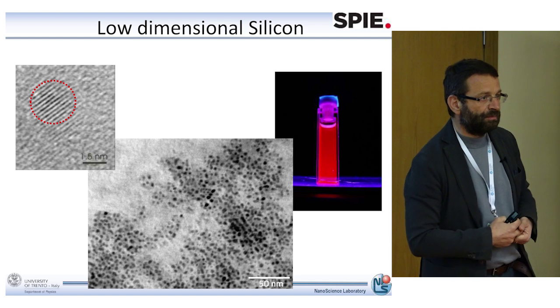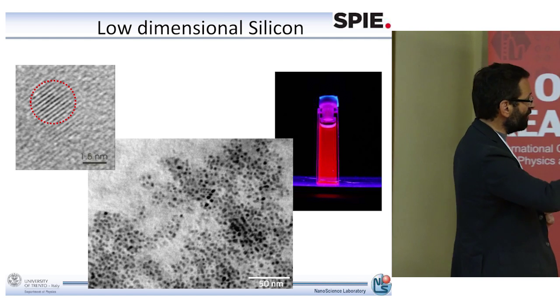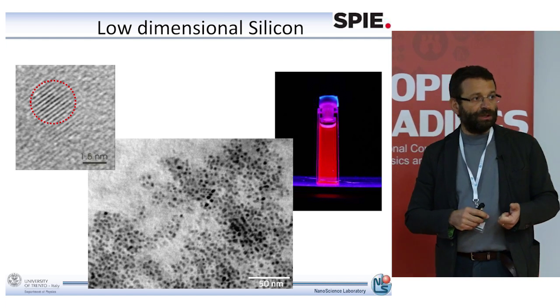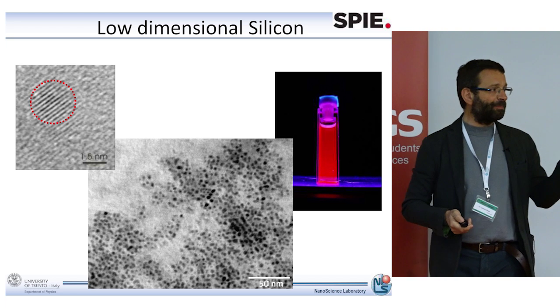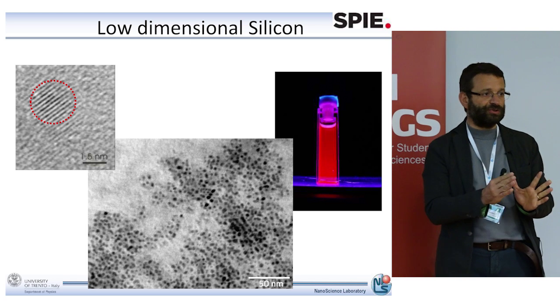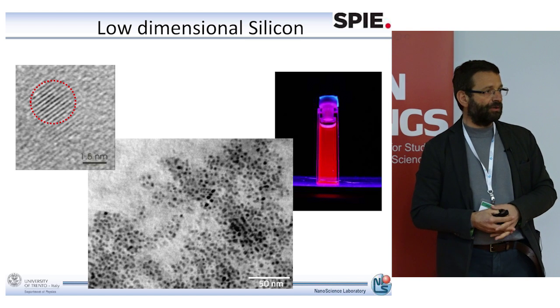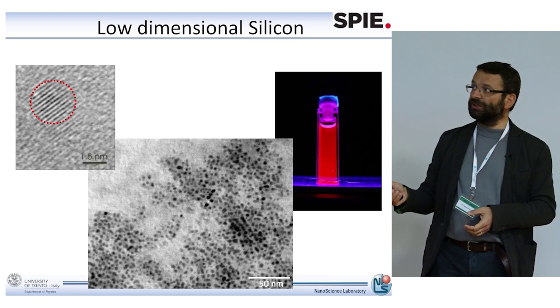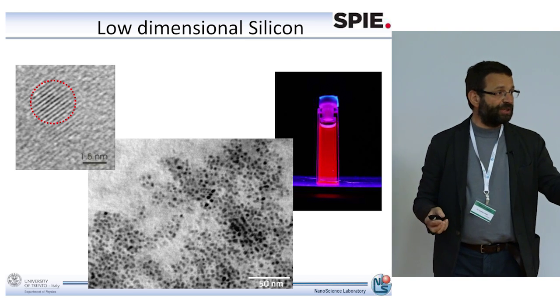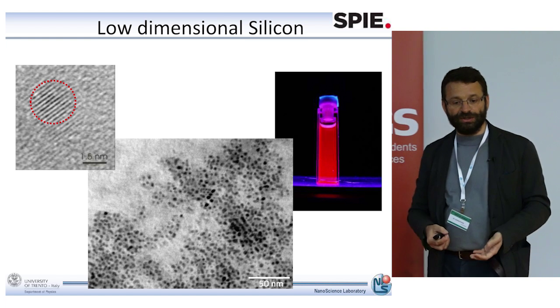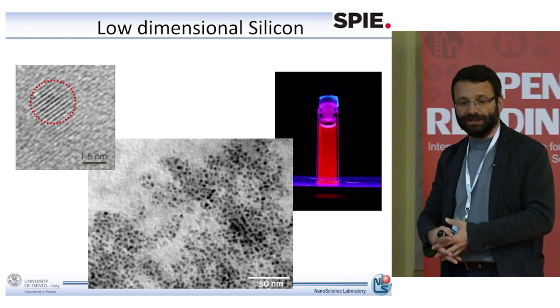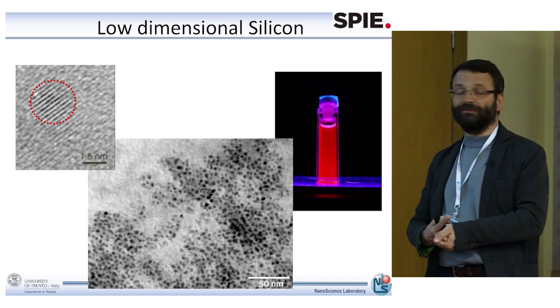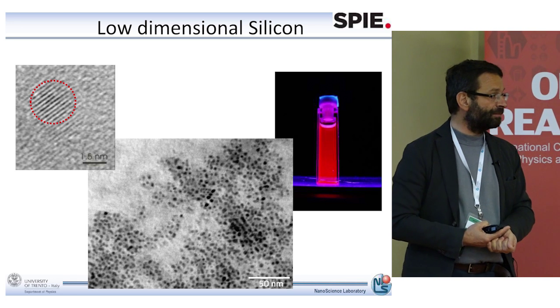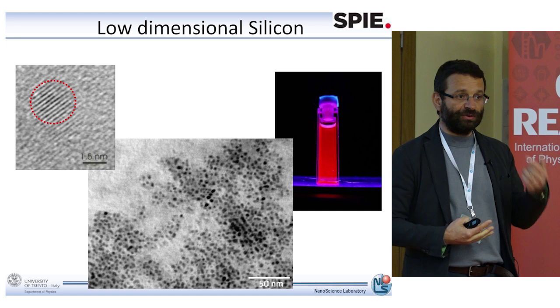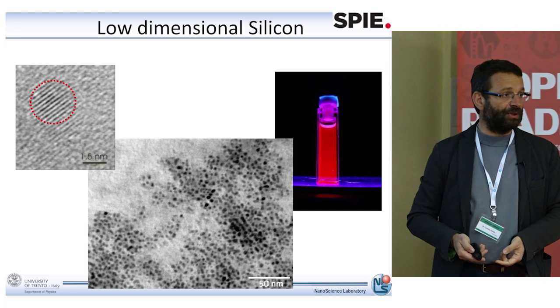Efficient, strong light emission. And the second fact is that the band gap of silicon is changed by reducing the dimension of the silicon nanocrystal. You see that the emission is in the red. If you do not change the band gap of silicon, silicon has a band gap of 1.1 electron volt, and you don't see anything. Even though it's emitting light, you don't see it because your eye is not able to see.